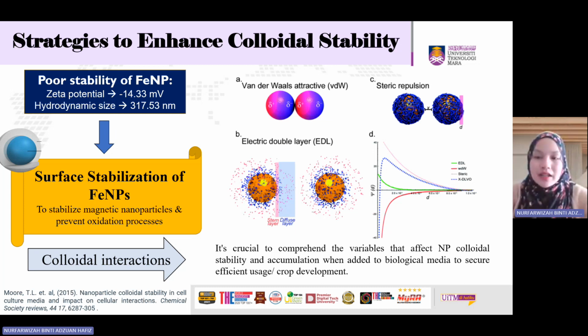According to the research findings, iron oxide nanoparticles exhibit poor stability and a tendency to agglomerate, with an average hydrodynamic particle size of more than 300 nanometers and a lower zeta potential of about 14 millivolts. Thus, the main method to prevent the agglomeration is particle coating with a capping agent to separate the particles using electrostatic repulsion.